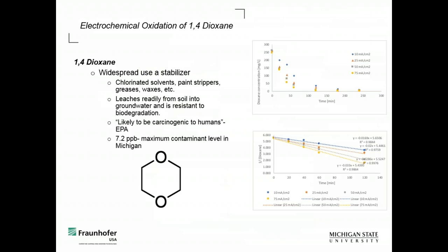One last thing is this is sort of newer data, but we're also working on 1,4-dioxane, which is another emerging contaminant. We've done current density studies, as you can see. Even at 10, within I think a little less than 4 hours, we've completely remediated the 1,4-dioxane. We're also looking at ion exchange at high levels because it is very efficient at removing 1,4-dioxane. We can regenerate it in the same manner that you do for PFAS. So we're looking at 1,4-dioxane as well.